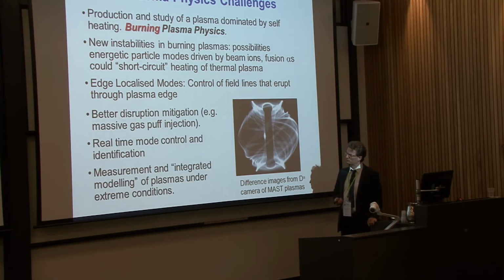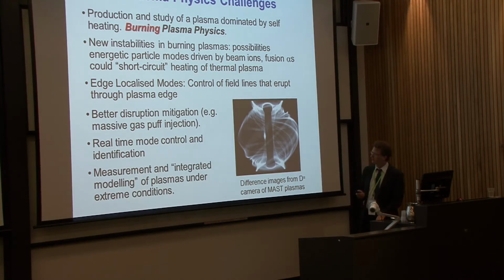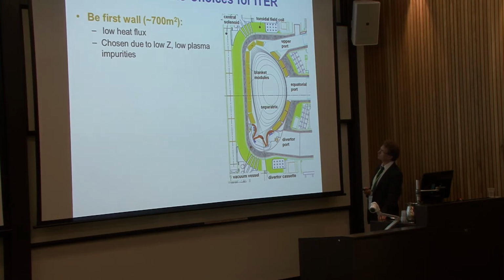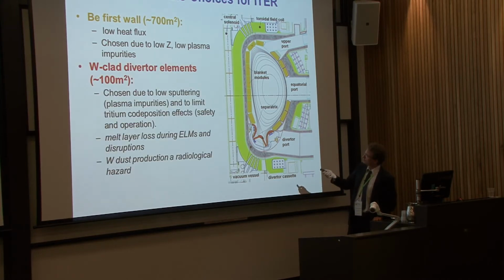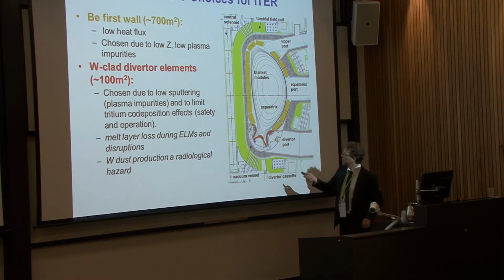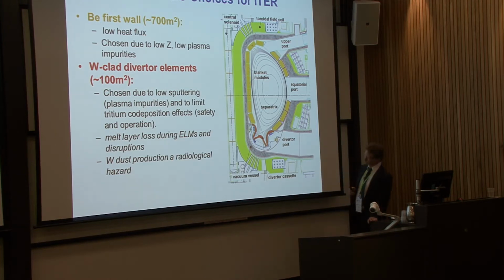Together with a combination of technology really for control and also modelling and integration. Here's some material choices for ITER. ITER will have a combination of this beryllium first wall, chosen because there's relatively low heat flux, but it's also low Z, so I want a low Z impurity. I don't want high Z in this, because if I have high Z in this, the machine will radiate like hell. The compromise, unfortunately, tungsten is high Z, but it was used down here because it has extremely good heat flux resilience, and it's melt loss resilient due to ELMs and disruptions.